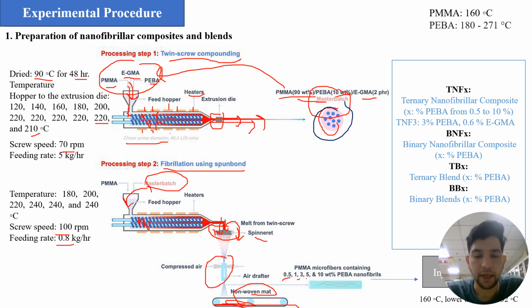After that, like this picture, it shows the filament, and inside it the fibers. This filament is a PMMA filament, and inside they just show the fibers of PEBA. So different concentrations of PMMA and PEBA nanofibers he synthesized, and after that they did injection molding at 160 degrees centigrade, which is lower than the melting temperature of PEBA. Okay, here actually the picture is there, so the video is there, so that's why it is hidden, but okay, I will try to explain.